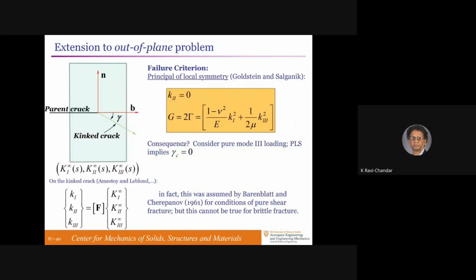Mode 3, on the other hand, is a more interesting, challenging problem. Same picture, I have the parent crack in the NB plane, and I want to know at what angle gamma will it kink. Now the loading is no longer in plane, it's out of plane, mode 3. So the applied load could be K1, K2, K3 super infinity. That means there's a locally perturbed value of K1, K2, K3, which depends on some geometric factor that depends on the angle gamma.